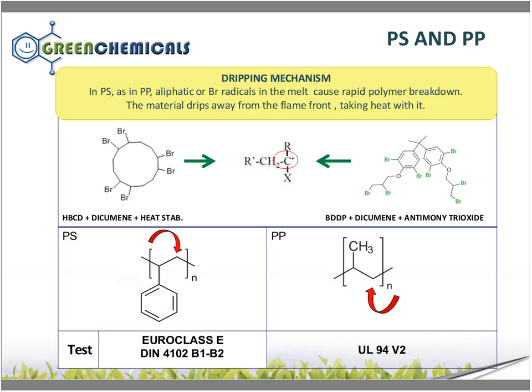Just to let you understand, I would like you to look at these two chemical structures. Our study began with the comparison between polystyrene and polypropylene. You can see these two polymers are very similar, and when we have to overcome mild tests like the V2 for the polypropylene and the Euroclass E for the polystyrene, the flame retardancy is obtained through a dripping mechanism. You look here on the left, a classic formulation used in polystyrene foams. It is composed of HBCD with a synergist, the dicumene, and a heat stabilizer. In the polypropylene, you can find BDDP, that is tetrabromobisphenol A bis(dibromopropyl ether), together with dicumene and antimony trioxide.